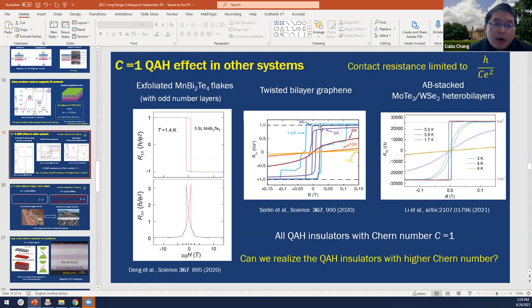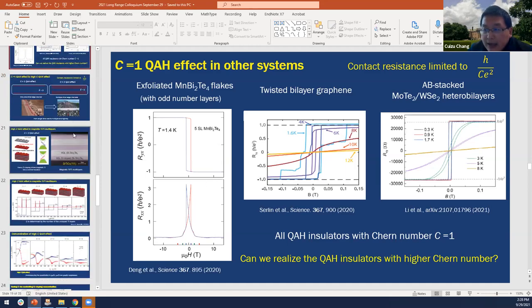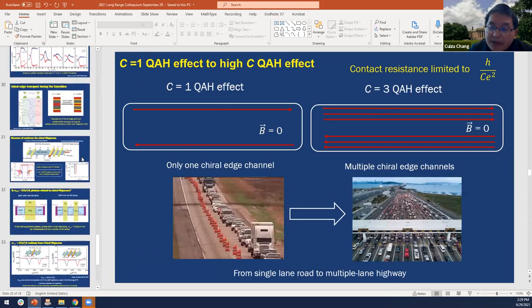In my opinion, the Hall resistance should always be lower than h over e squared, in particular when the longitudinal resistance is finite. And I think that might be because of some disorder or some defects in the twisted bilayer system. That's just my understanding. And for this kind of high precision measurement, I think the magnetically doped TI or this kind of intrinsic magnetic material might be much better than the twisted system. And the magnetically doped TI is easier to reproduce. That's my comment.